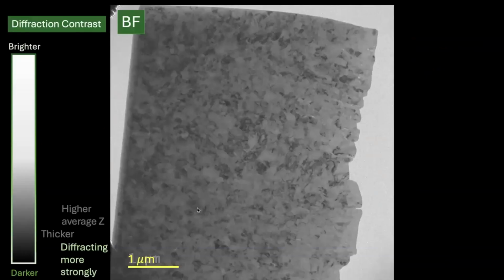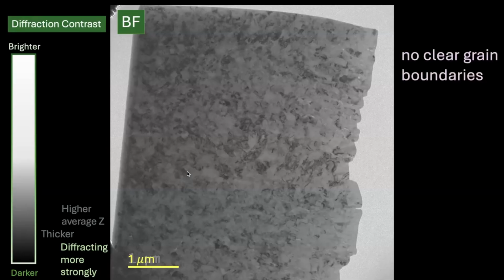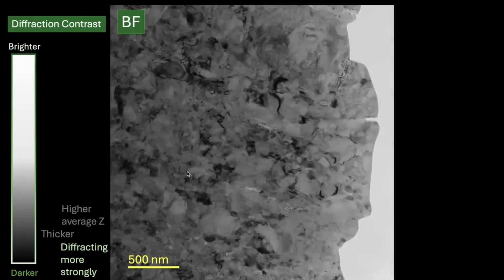This is the Reidite granule sample, these orange things in the middle here, indexed as Reidite in EBSD. So here there are no clear boundaries between the granules. The individual granules have varying diffraction contrast. There's kind of a linear fabric, and there are these tiny dots in what looks like fractures. I will go into those. So this is polycrystalline, and it has pretty high strain in some of the granules. This is our first piece of evidence.